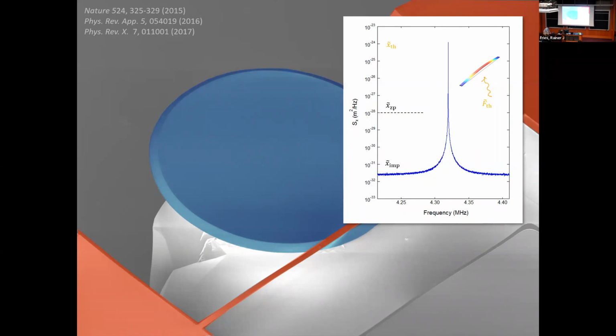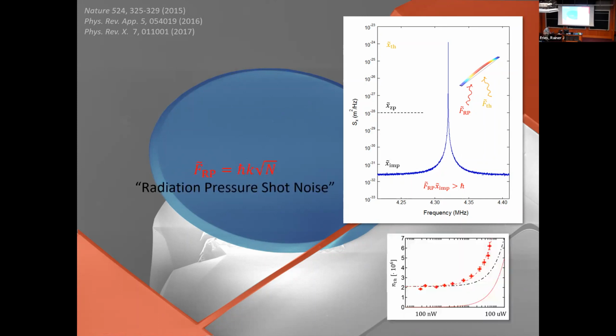So in this regime, we're making a very strong measurement of the mechanical motion. In fact, in principle, with this measurement, we could resolve the zero-point motion in maybe 10 times the thermal decoherence time. And in that regime, actually, the fluctuations of the radiation pressure force due to shot noise, the so-called radiation pressure shot noise, starts to actually overwhelm thermal noise. So if you actually measured the area underneath this peak, you would see something called radiation pressure shot noise manifest as a heating of the mechanical resonator.